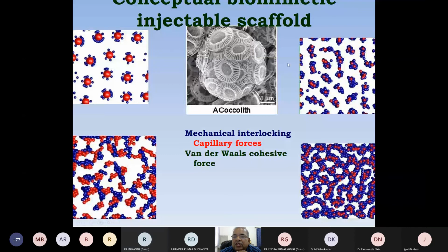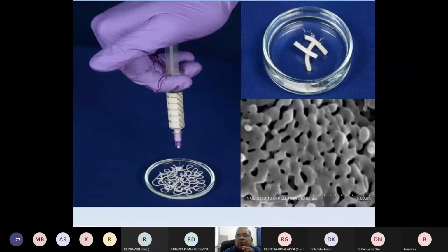Thank you. So what we thought was, if we can bring those biomimetic hydroxyapatite particles together in a paste form, the polymers coated on the surface of the particles will cross-link themselves physically and form a continuous network, and without any cementing action, they will form a three-dimensional network. This was with the help of mechanical interlocking, capillary forces, van der Waals interactions, and so on. This was the concept, and we could do that.